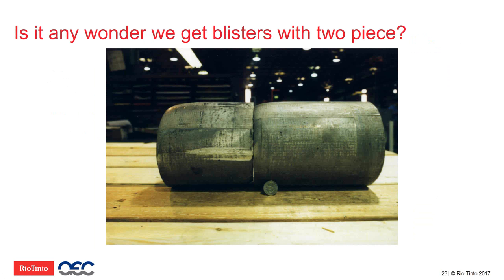So proper shearing, if that's the process used to cut the log into little pieces of billet like we see here, and also the cutting angularity have to be considered. If a shear cannot cut square short pieces, it cannot supply any two-piece billet. And the reference I typically use is less than half a degree per 4 inches. So less than half a degree per 4 inches, no more than that.